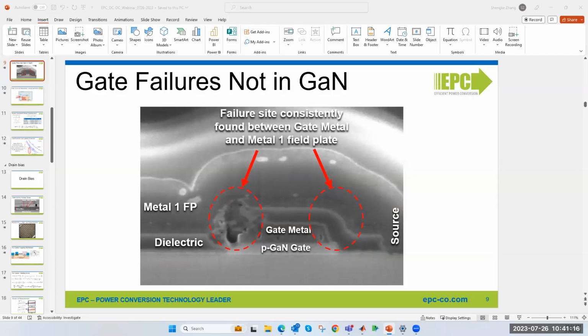And also the reason you want to avoid using negative turn off is because during the dead time, the reverse conduction voltage drop, although it looks like a diode, is a slightly different mechanism, and so the voltage drop is higher. If you use negative drive, that negative voltage gets added to that voltage drop during the dead time, which will add to dead time losses. So it's not needed to avoid the shoot through, and it's detrimental in terms of losses. So all of our designs and all of our reference designs always implement 0 voltage turn off, which also makes the gate driver easier.